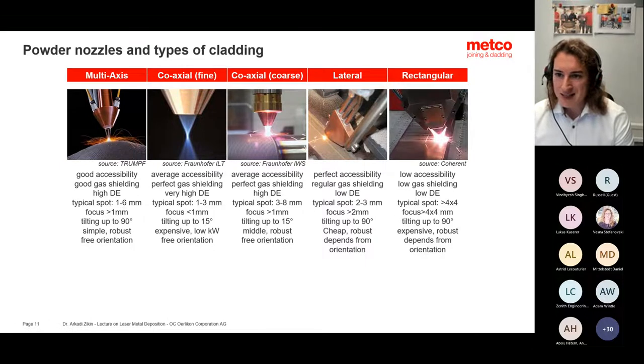We had multi-injection hole nozzles, which have different names, multi-axis, whatever. The most important thing is that we have, under a certain angle, a certain number of injection holes, which starts from 3 and can go up to 7. If you look at the nozzles on the market, quite a couple of companies deliver them, and some of them are very successful nowadays. You also had coaxial nozzle supply, which always had a huge advantage, the highest deposition efficiency, but let's say lower working lifetimes. Everything started with so-called off-axis nozzles or lateral nozzles, where you just had a powder supply not interacting with the laser before it interacts with the surface.